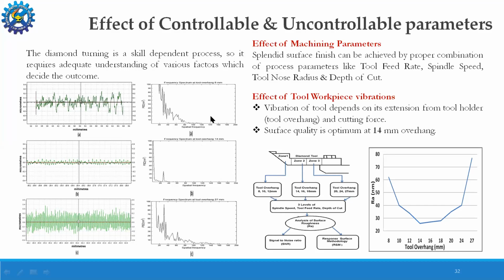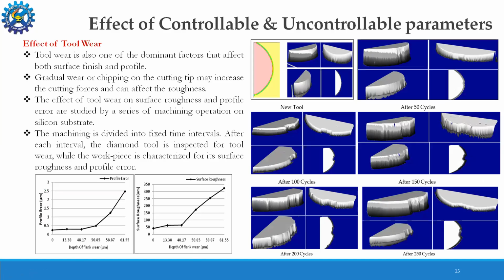This is at 8 mm, this is at 14 mm, and this is at 27 mm. So we can see that very few random frequencies are present at 14 mm, which leads to an optimum surface quality in comparison with the 8 mm as well as 27 mm. So this is one of the most important parameters through which we can optimize or reduce the effect of vibration in any optical component.